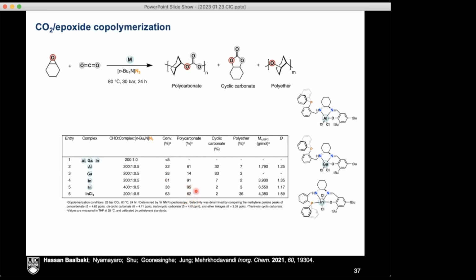And what he was able to show is that comparing this to indium chloride, the ligand does do something. So this is always really important to compare, because Hassan's first project was just using simply indium bromide and tetrabutylammonium for cyclic carbonate formation, which is not something I'm talking about here. But there, ligands don't do anything. Just indium tribromide itself is an excellent catalyst for cyclic carbonate formation. So for us, we are a little bit paranoid. It's like, is the ligand even doing anything? And in this case, it absolutely is doing something.